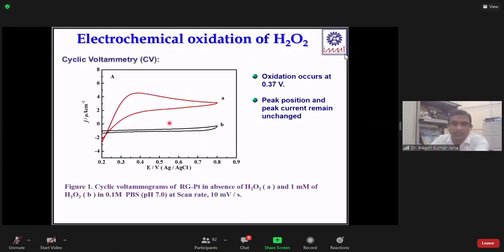So here what we did, after synthesis of this branch platinum nanoparticle, you put it on the graphene surface and check how it is helping for hydrogen peroxide sensing. You can see when you put the branch platinum nanoparticle with the graphene, the oxidation potential is lower than the previous one. Previous one is 0.45, now you see 0.37. So now it is decreasing the overall potential.